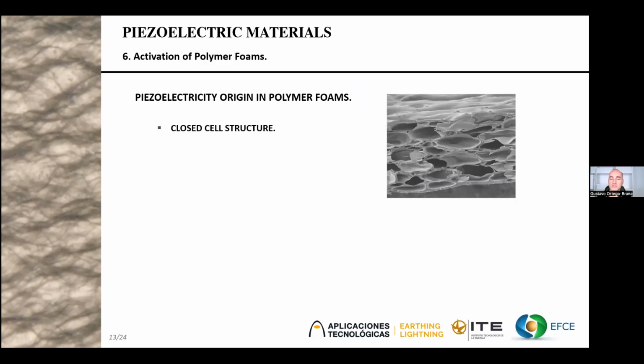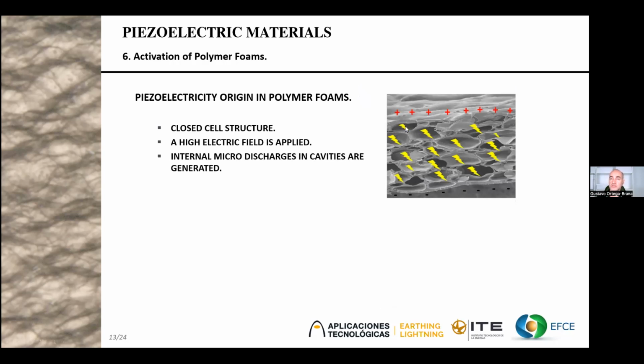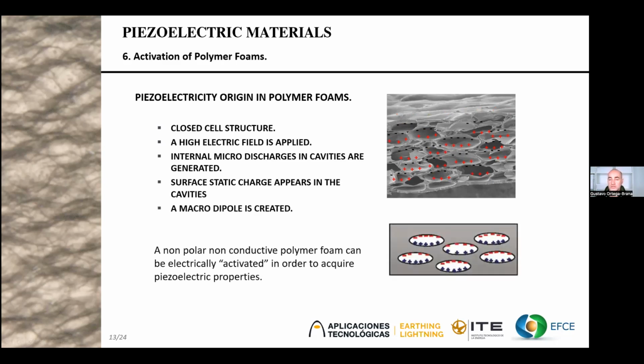The origin of piezoelectricity in this kind of material is based on macrodipoles created by electrical discharge inside the bubbles of the structure. When an electric field is applied across the thickness of the material, electric breakdown, as we see in these lines, is produced in the bubbles, separating charges on the walls inside, on the top and below. The charges are of opposite sign on the top and below of the bubble. That is how the macrodipole is produced inside the bubble, and then this charge is retained permanently, for many years.